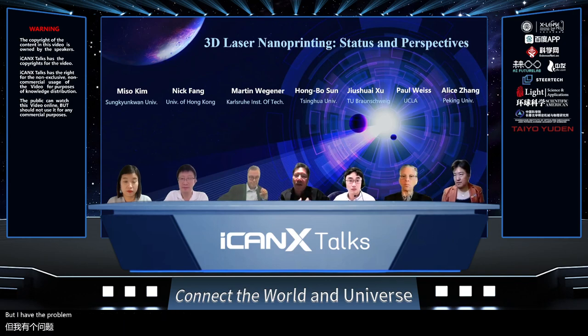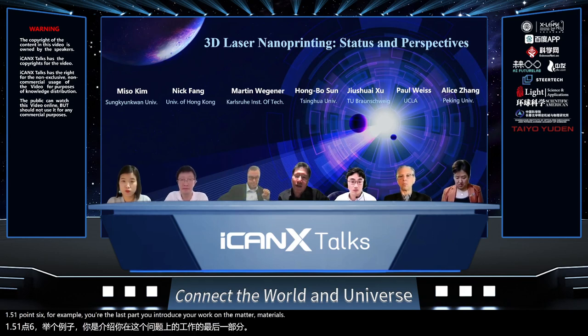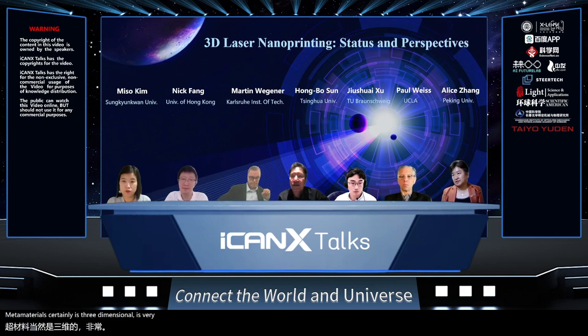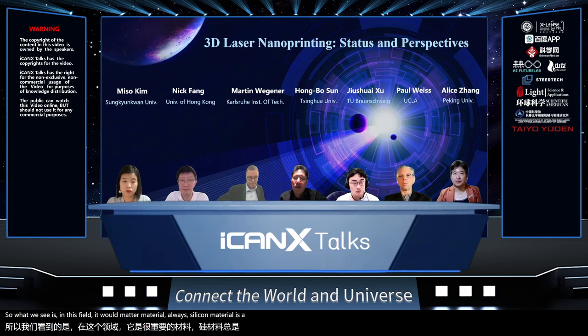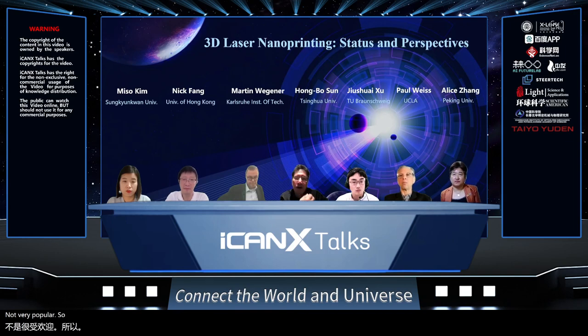But I have a problem. For polymers, the refractive index is always low, 1.5, 1.6. For example, in the last part, you introduced your work on metamaterials. Metamaterials, certainly in three dimensions, are very important. But the problem is you cannot tune the refractive index very far, because the maximum refractive index is limited. In this field, metamaterials are always made of silicon. Even though with two-photon polymerization we can do 3D, three-dimensional metamaterial is not very popular. So I wish to hear from you: what will be the biggest application for this polymer-based 3D structure?